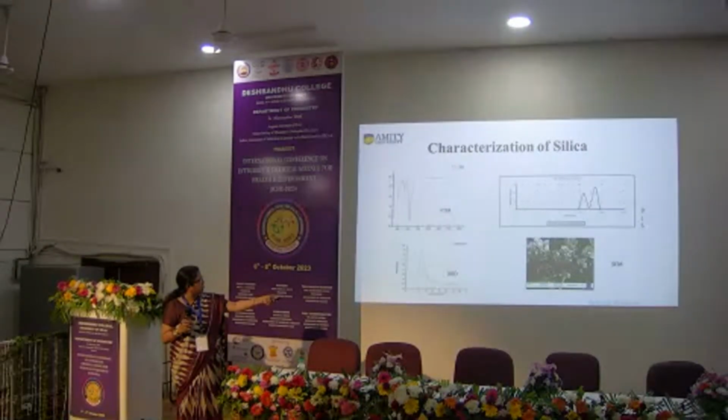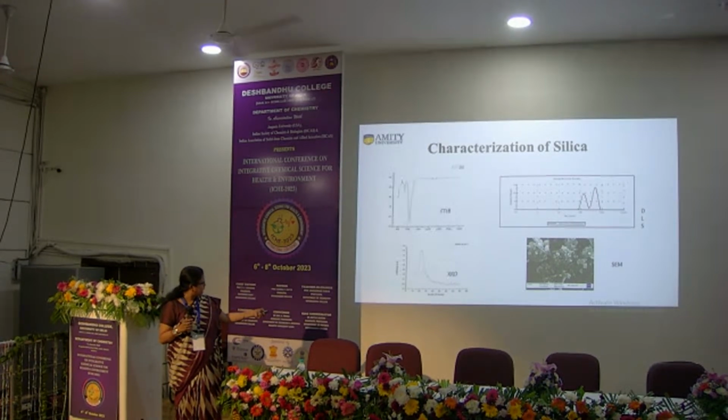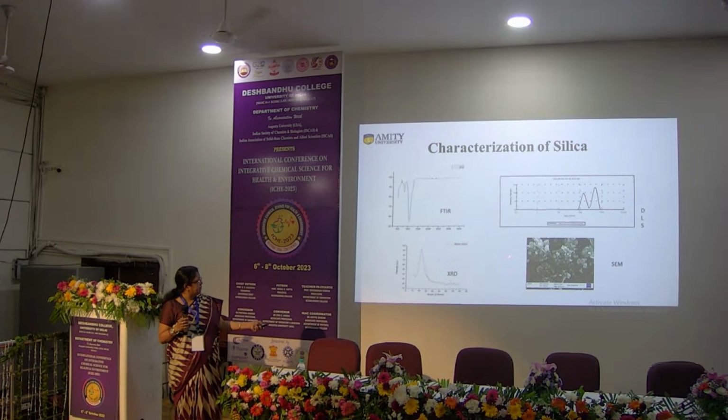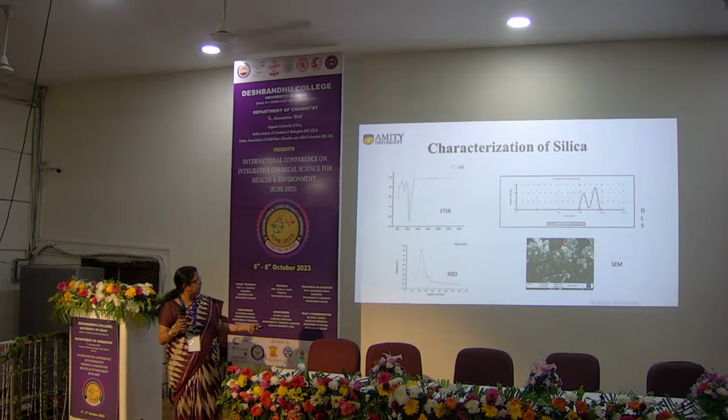The average size range is around 300 to 400 nanometers. This study shows the standard silica peak around 22 degrees 2 theta. FTIR shows the Si-O bonding in this range, and this is the SEM of the nanosilica we have synthesized. That is, spherical nanoparticles we have obtained.